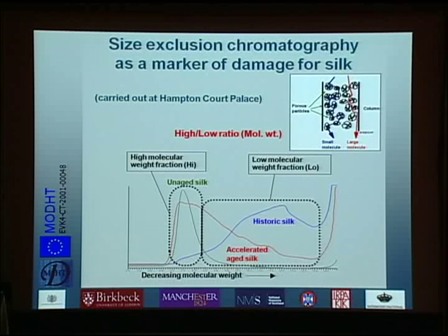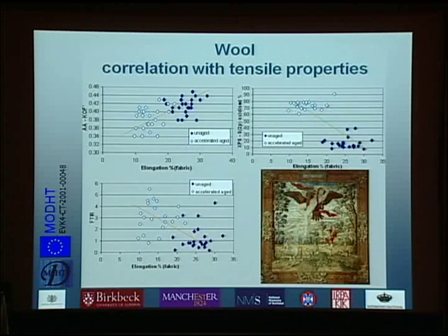Size exclusion chromatography, which was exclusively used for silk, is a measure of the molecular weight distribution, and a very useful marker of damage is the high over low ratio, so the fraction of high molecular weight to low molecular weight, which really tracks how the protein chains become shorter as the silk ages. I'll show these graphs now